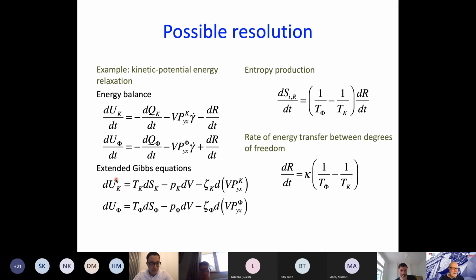And in the steady state, we could postulate that there are extended Gibbs relations for the thermodynamics of this system, where we have a Gibbs equation for the kinetic energy bath and the potential energy bath. Now what that gives you when you work it through is an entropy production that's related to the temperature difference between the potential energy heat bath and the kinetic energy heat bath. So if they differ, and if heat is being transferred from one to the other, then there'll be entropy production. And we can postulate a constitutive relation that describes the rate of energy transfer between two degrees of freedom, and kappa here would be an energy transfer coefficient that plays a similar role to the thermal conductivity, but this is for internal degrees of freedom instead of spatial transport.